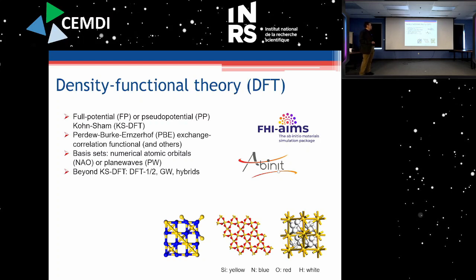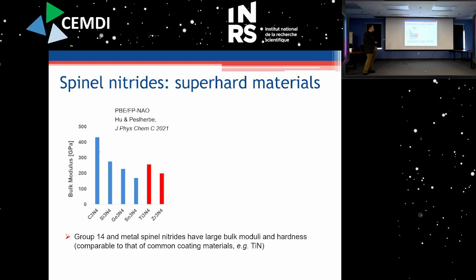And so we'll be looking at silicon hydrides, oxides, nitrides, and all this work really started, or was motivated, by some findings about carbon nitride and the zinc blende carbon nitride structure, which was reported to have a very, very high bulk modulus and hardness, so a very hard material. Indeed, if you calculate the bulk modulus of carbon nitride, it's very high. But this is true for essentially all of the group 14 elements or other metals, either titanium or zirconium. So all of the group 14 and metal spinel nitrides really have very large bulk moduli.